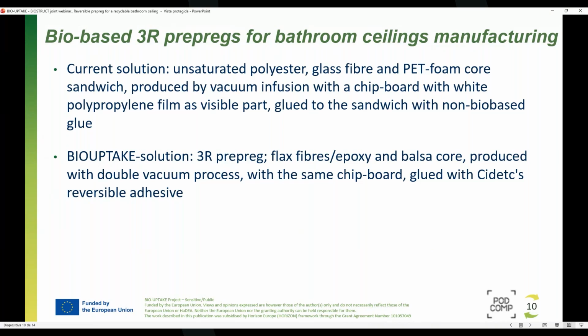The BIO-UPTAKE solution that we have worked on together with our partners is the 3R prepreg, which contains flax fibers and bio-based epoxy. And we use a balsa core to produce a sandwich to replace the ceiling of this bathroom, and we produce it with a double vacuum process, and it has the same chipboard glued with reversible adhesive. Next slide.